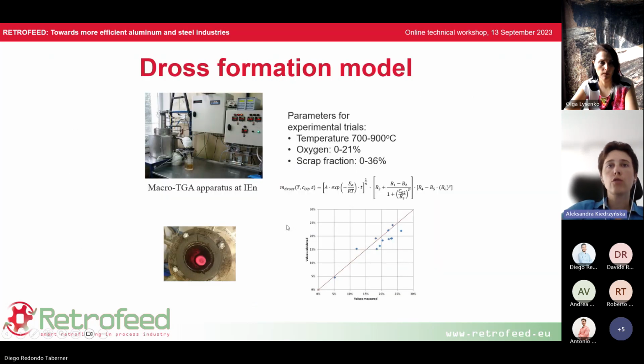Due to the lack of any model of dross formation that can be applied for assessment of dross amount, it was necessary to carry out some experiments and develop the model based on that. We did these experiments in our laboratory scale macro TGA for different parameters of temperature, oxygen and scrap fraction. Based on that, we obtained some empirical correlation which allows at least to estimate the quality of the product. The comparison between measured and calculated values is presented in the figure below. This dross model was also implemented in Modelica and integrated into the digital twin. Next, please.